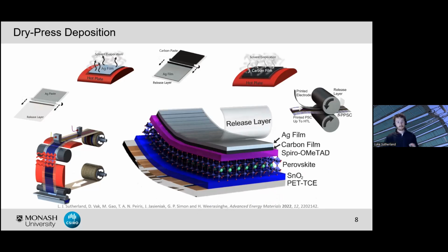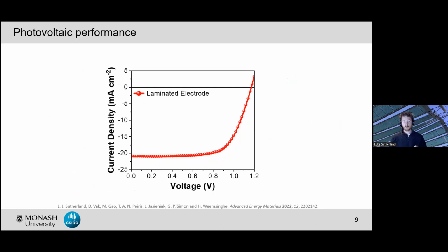And so the main benefit of separating these two fabrication techniques is we're able to mitigate that risk of solvent leaching and also high temperature processing, which you would need to dry these carbon films. And both of these processes can be detrimental to the performance of our perovskite solar cells. And so by using this technique, we're able to achieve some pretty awesome results and demonstrate the world record efficiency for a roll-to-roll printed perovskite solar cell up to HTL with a vacuum-free electrode, achieving a maximum efficiency of 16.7%, which was a really exciting achievement for us.